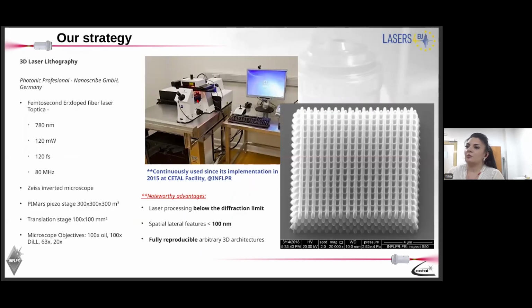To reach this goal, we use an equipment which is called Nanoscribe. It's a kind of 3D laser lithography system using a femtosecond laser with a high repetition rate, which is focused on the sample through an inverted microscope, through different microscope objectives as a function of the spatial resolution that we want to achieve, as I will explain to you in the next slide. This system is available at CETAL facility, and it's been working continuously for the last 10 years, and it's still working very well. This technique is known for several advantages, such as we can get 3D structures with lateral resolution below 100 nanometers. We can process materials below the diffraction limit, and which is very important for biological studies, for in vitro studies, is that our structures are fully reproducible because they are assisted by CAD.